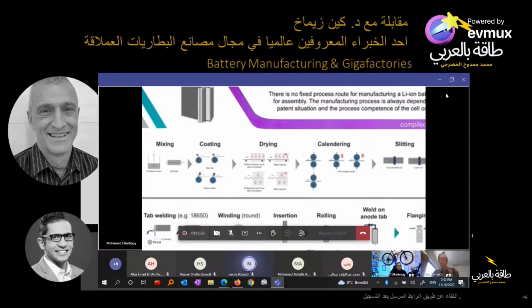Well, this is not digital. It's not like, oh, too much, oh, too little. No, if you expose it to some moisture in the air, what happens? Well, you get some lithium hydroxide, you get some metal oxides. So what? Well, your capacity goes down. That water in there will also react with one of the salts in the electrolyte that'll form hydrofluoric acid, which degrades your anode and your cathode, and your capacity is less and your cycle life is less. And yeah, it's not like the cell dies. It's not like the cell explodes because it was exposed to water. It's just not as good of a cell.